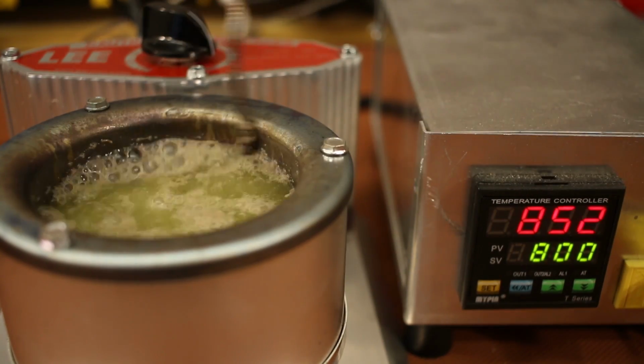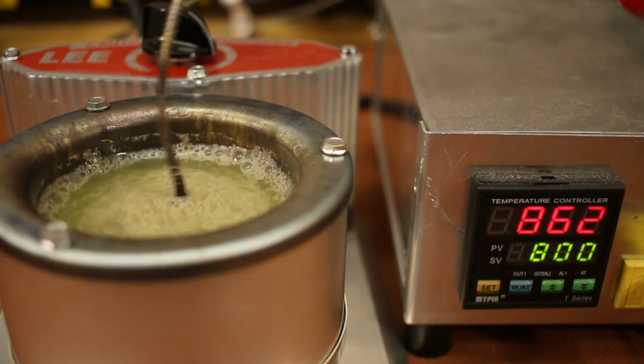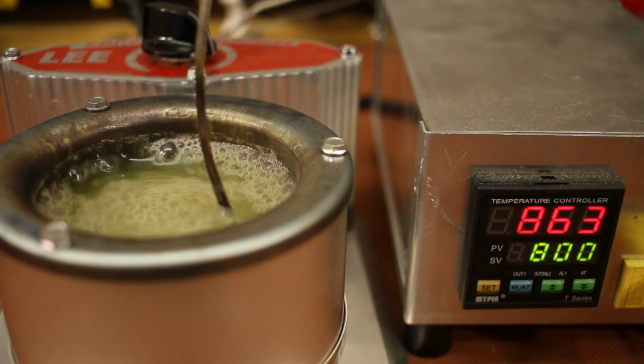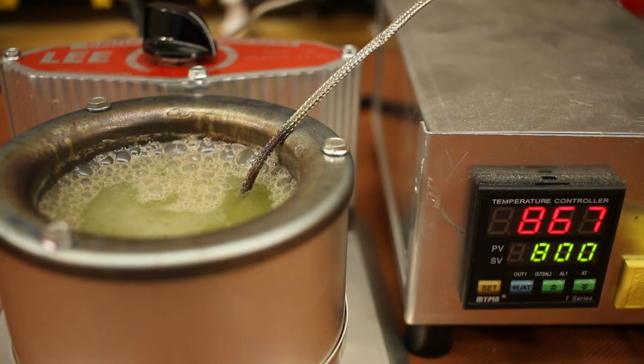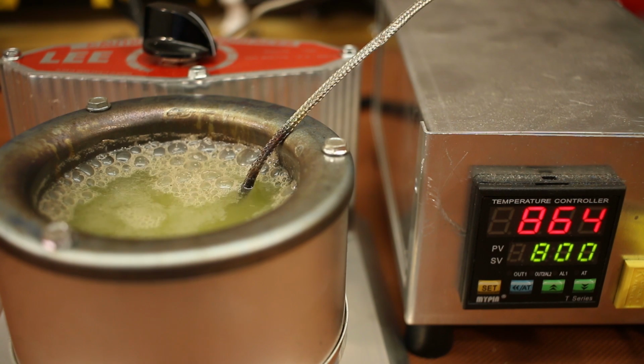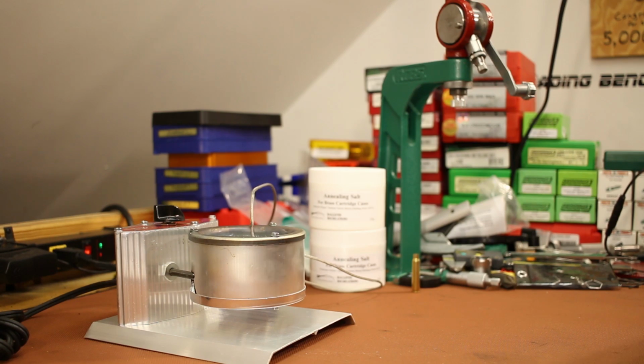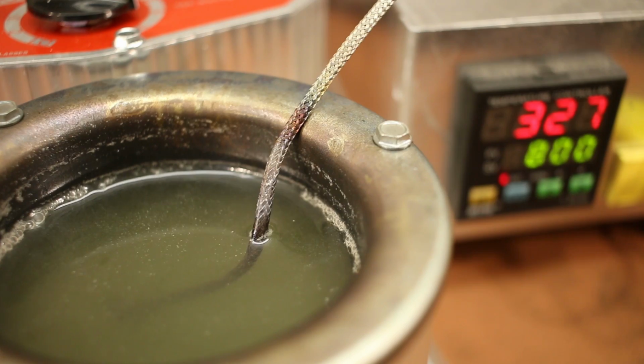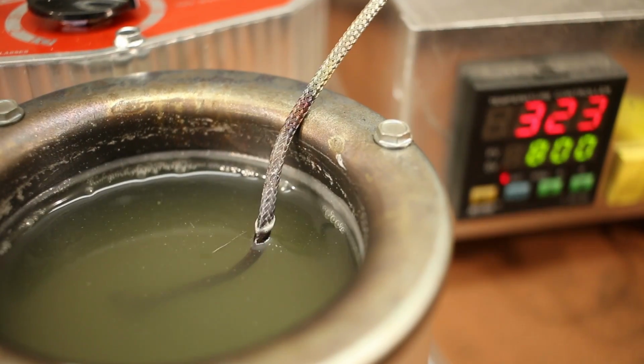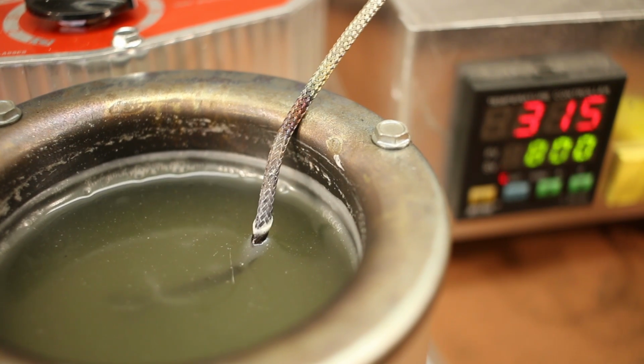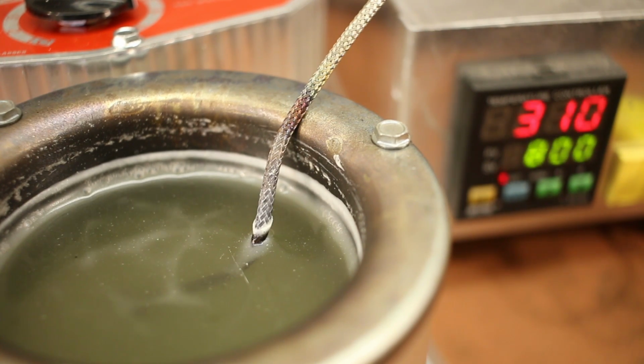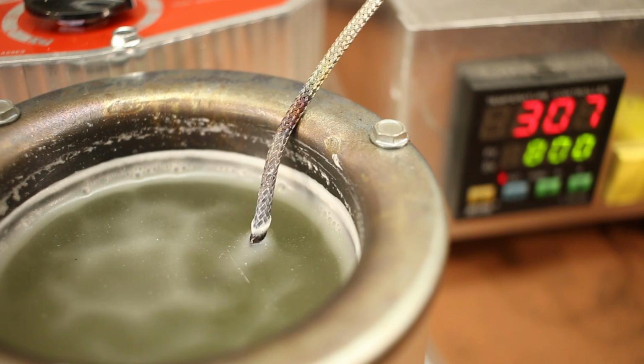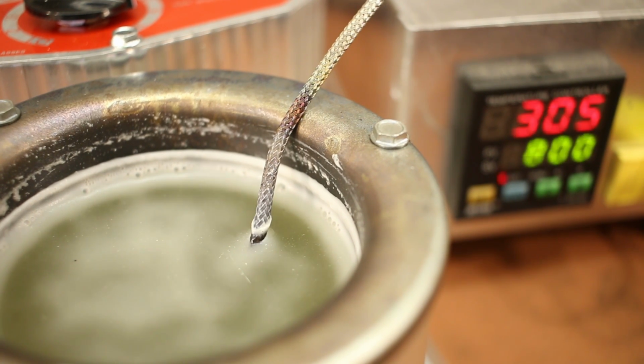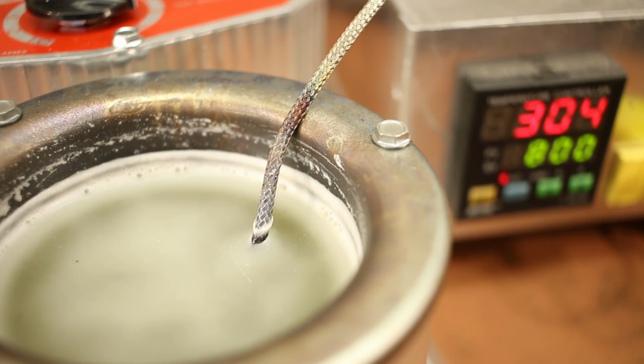And as it melted down, I kind of gave it some stirs. It gets a little bit foamy at first, and then over time, the foam goes away and you end up with a yellowish kind of clear liquid. So that was the first step, to get it melted down for the first time, and then I let it all cool down and solidify. Watching the PID controller as it cooled down, it seemed to freeze right about 300 degrees Fahrenheit. So that's pretty close to the 142 degrees Celsius, which is 288 degrees Fahrenheit that he says it should freeze at. So yeah, that all made sense.